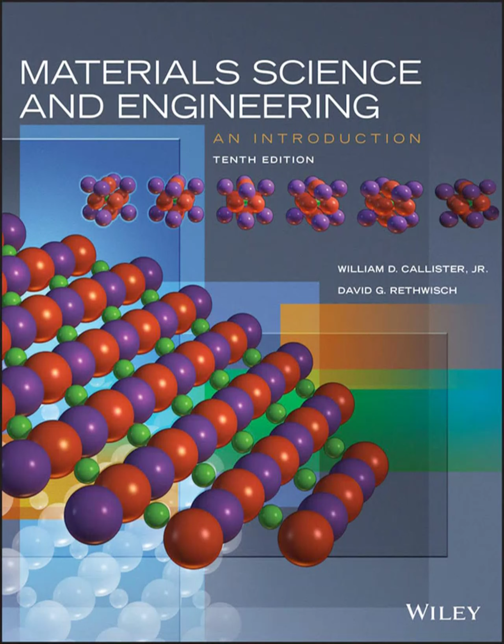And this is often achieved using a carefully controlled two-step diffusion process. First, there's pre-deposition. In this step, impurity atoms, maybe boron or phosphorus, usually from a gas source, diffuse into the silicon wafer. Crucially, the surface concentration Cs is kept constant during this phase. So we're back to using that error function solution to Fick's second law we talked about earlier. Okay, so load the surface and let some diffuse in.